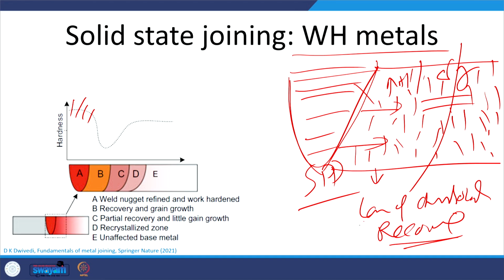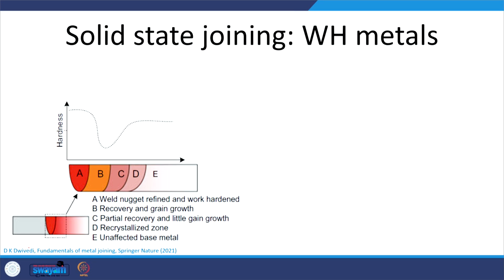So, it is the recovery that causes the loss of these dislocations, and that in turn causes a significant drop in zone B of the joint of the metal which is work hardened, or strengthened by work hardening. The ferrous metals respond very significantly to the solid state joining process, because not just work hardening takes place, but also deformation assisted phase transformations due to the typical weld thermal cycle which is imposed. So, if we look at the different zones which are formed in the WH metals,